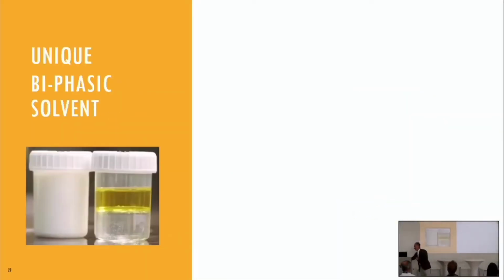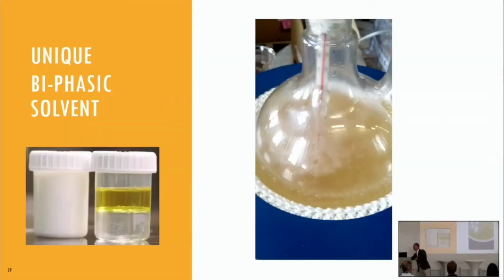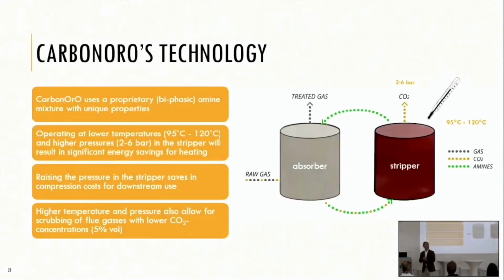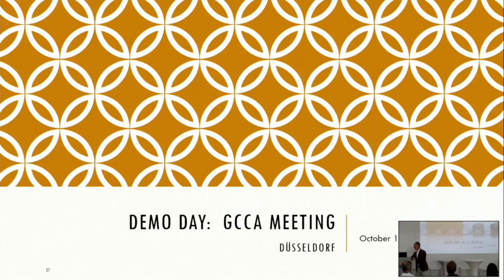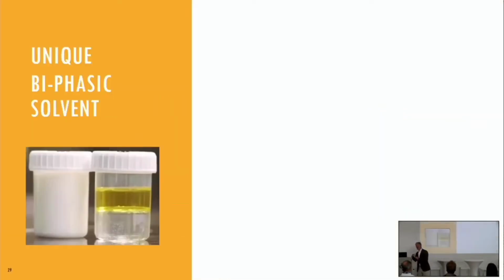If you look at the uniqueness of the biphasic solvent that we use, you see it on the left side at 40 degrees. It looks a bit milky. It's a very thin emulsion, but when you heat it up, it splits in two fractions. It actually looks like a spoiled mayonnaise, so it's oil and vinegar on top of each other. And the nice thing from the carbon capture perspective is that the CO2 is not contained in layer number 1 and not contained in layer number 2. So it actually bursts out of these two layers.